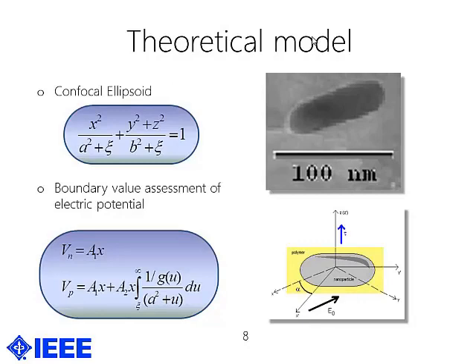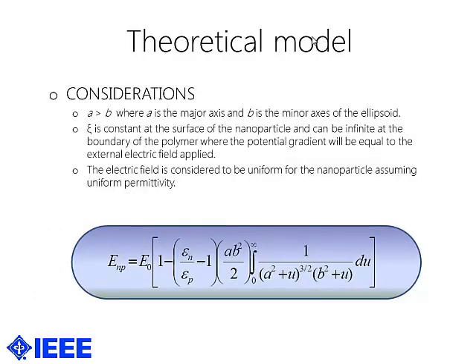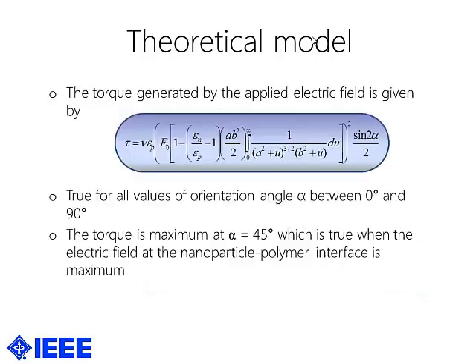and we performed a boundary value assessment of the electric potential acting on this particular nanoparticle, and we were able to come up with what is going to be the ensemble electric field applied to the whole material composite. So I'll rush through this equation because it's going to be too descriptive. And finally, the torque that's going to be applied to the nanoparticle, thereby orienting these nanoparticles inside the polymer matrix, is going to be maximum at an orientation angle of 45 degrees.